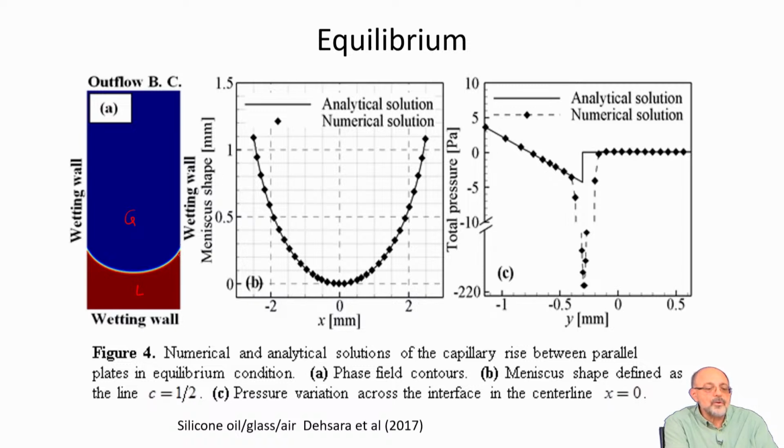Well, solid walls and a horizontal substrate all have the same properties, and we are just using the phase field model to find the equilibrium. The good thing here is that we have an analytic solution for equilibrium. So at least we can test our phase field model on an analytic solution, and it works perfectly. As you can see here, this thin white line is our interface thickness. That's where we change from red to blue.